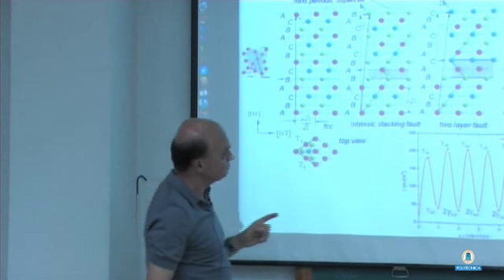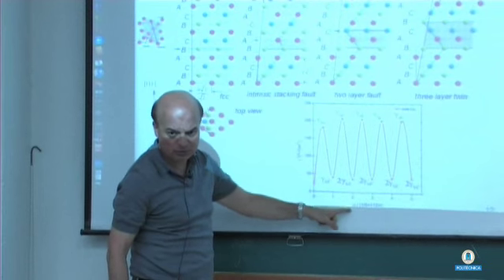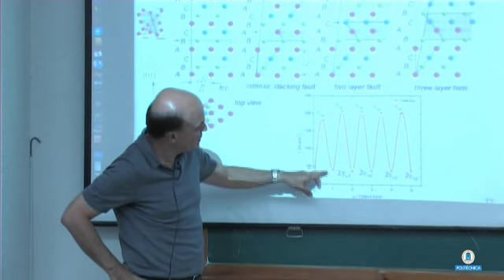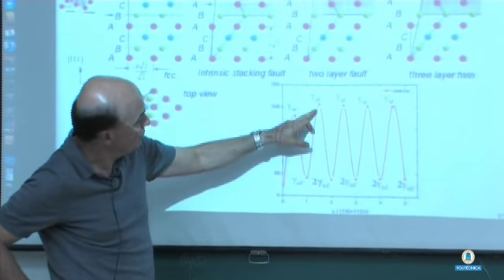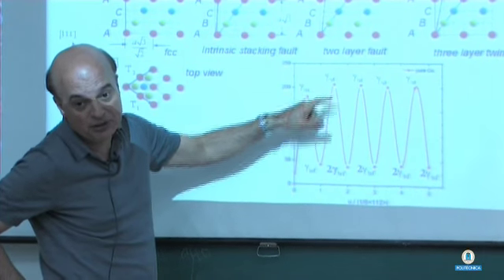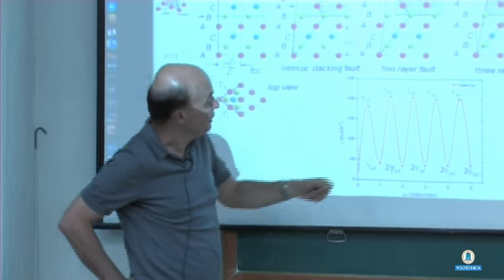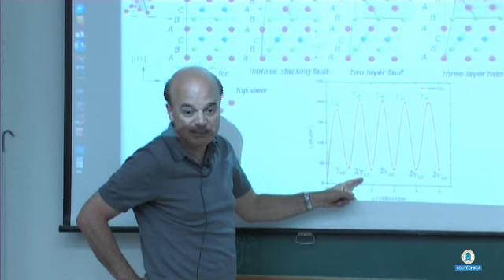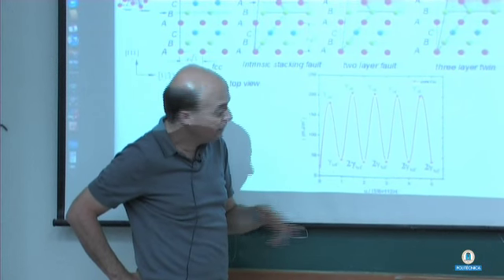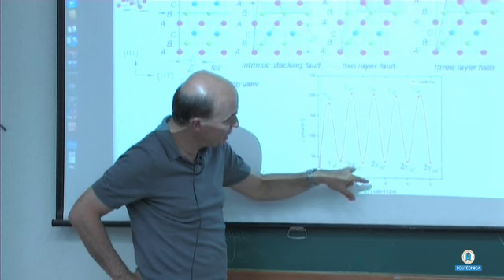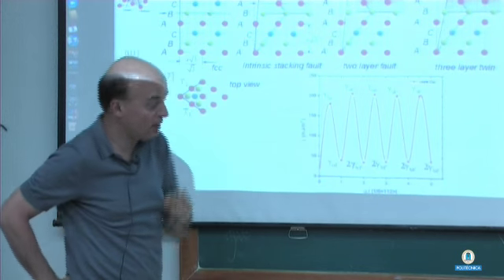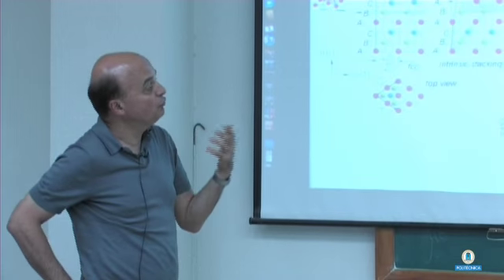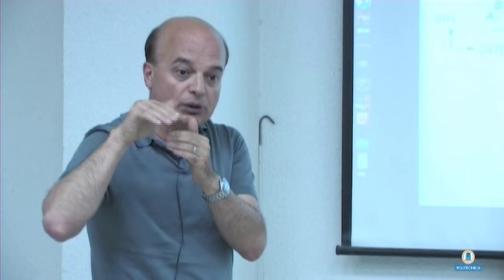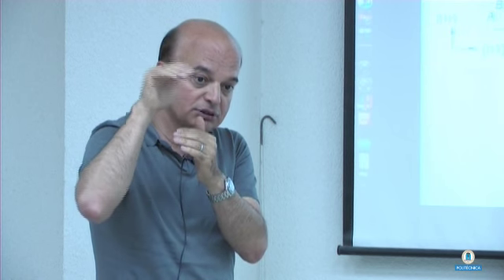And then if you look at the gamma versus displacement plot, we went through gamma US, gamma ISF, and then you go through another peak called gamma UT, and that's called the unstable twin energy. And then you go through a minimum which is called 2 gamma TSF, that's the twin stacking fault energy. And 2 times that, 2 gamma TSF, is equal to gamma ISF for pure metals. Okay. So this is the formation of a twin by a successive motion, or successive passage, of partial dislocations on subsequent layers.